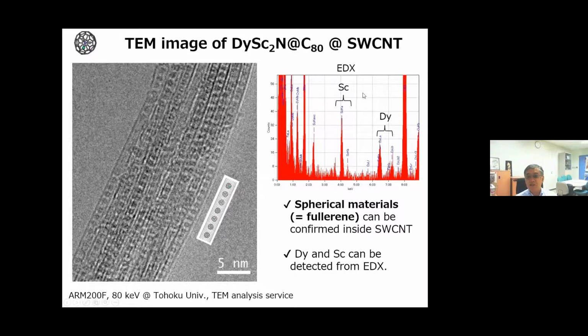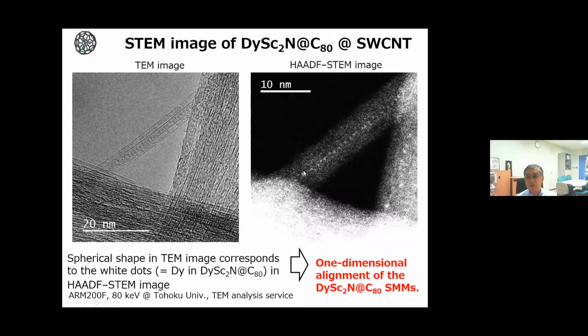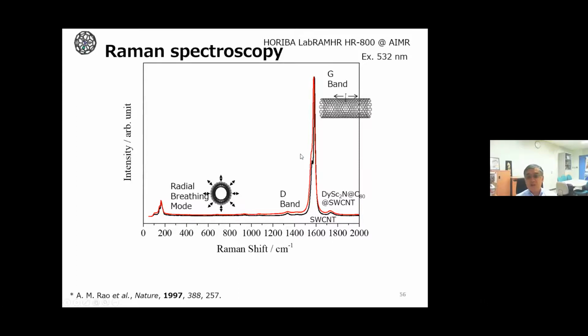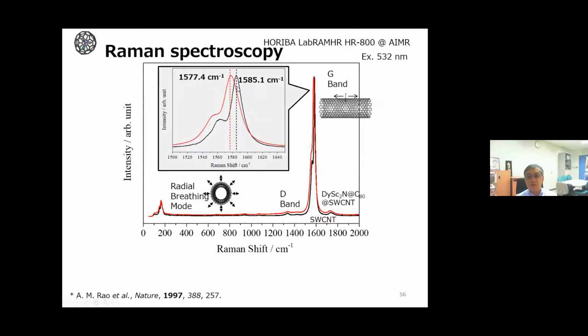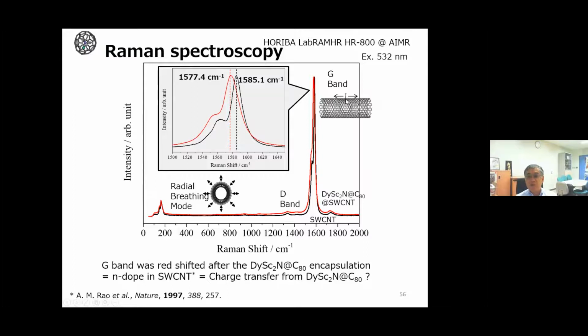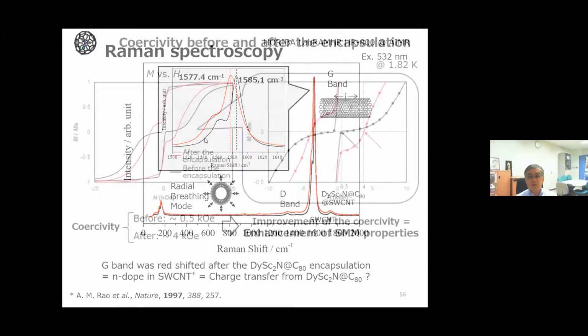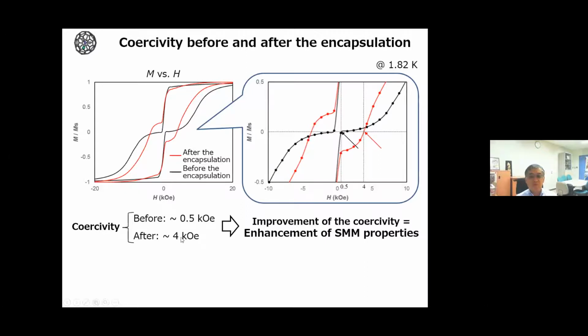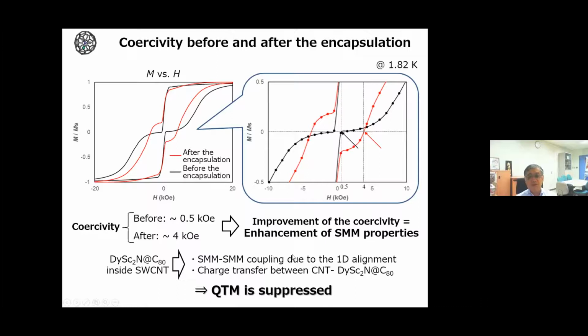So this is EDX, scandium and dysprosium included. And this is a HAADF-STEM, bright spotted metal fullerene single molecule magnet. This is Raman spectroscopy. This is very powerful. So you can see the Raman shifted before and after encapsulation because charge transfer occurred from the metal fullerene to the outside single carbon nanotube. Then Raman shift is observed. So interestingly, coercivity before encapsulation 0.5, after encapsulation 4 kilo, almost 1 order increase. This means that quantum tunneling is suppressed. So the quantum single molecule magnet is enhanced.